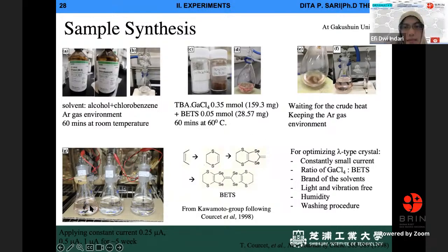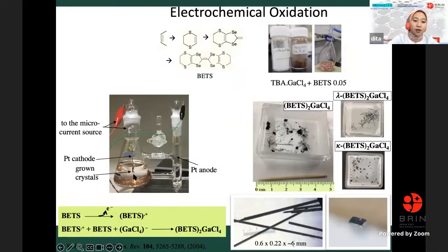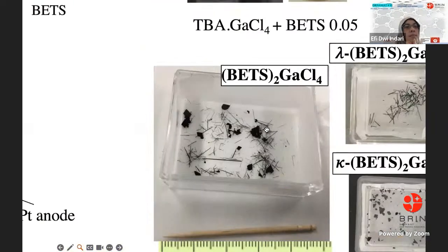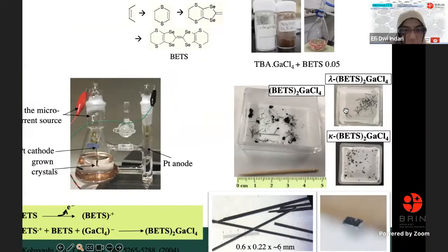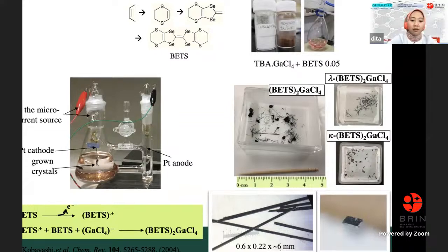Then the crystal grows on the electrodes. You can see this. I also produce very small single crystals, so I need to repeat such a synthesis procedure for my muSR experiment. From one batch, for example, you can see two morphologies like this. Maybe this is a question from Dr. Effie as well. There is a needle and there is a plate. This turns out to be very different arrangements of the molecules inside. For lambda, it's a side-by-side dimer, as I explained. But for kappa, it's a 90-degree rotated dimer. The facet is plate-like for kappa, but needle-like for lambda. So you can distinguish them. Hope it answers your question.